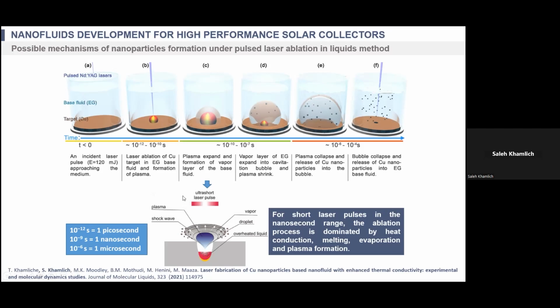As I mentioned to you, the pulses of the laser are very short. In our case, we use nanosecond and picosecond lasers. In South Africa, we use nanoseconds. In Germany, we use picosecond lasers. These pulses are very fast, highly energetic. Once they interact with the surface of the metal, they can melt it. The energy will be absorbed, of course, by the metal, which leads to the melting of the metal. Other pulses come in, they cause that melted metal to create what we call a plasma, and you will have shock waves happening around, and the process is just very fast. For short laser pulses in the nanosecond range, the ablation process is dominated by heat conduction. That's why the surface is melted, and evaporation, of course.